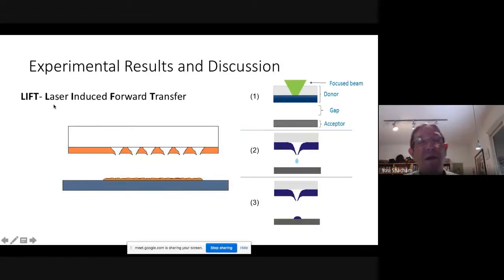So this is called LIFT. And because we have a laser, and you're taking your substrate, it's called a donor. And from the donor, you are generating metal drop. This is like an inkjet printer. But instead of having a cassette, we have a substrate of glass with gold. And we put drop, drop, drop, drop. We can put more than 100,000 drops per second. And you can put many drops. You can take many beams of the laser. So you can work very, very fast. And this is a commercial product.